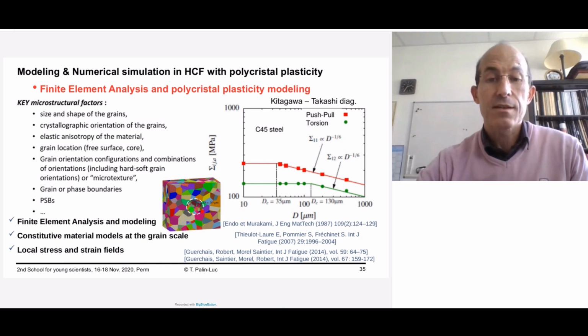competition with a defect. You can see here a volume with a defect in the middle, which is a hemispherical defect with diameter D, 50 micrometers. And the challenge is to reproduce the Kitagawa-Takahashi diagram, which illustrates the effect of the diameter of the defect on the fatigue resistance. So this can be done numerically, fully numerically.